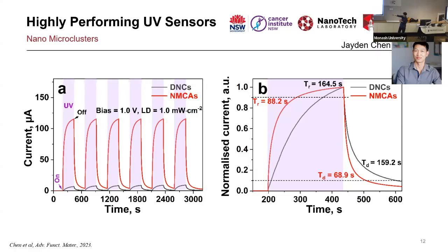And you can see the one in black is before we put the 5 microliter droplet, and the one in red is after we modify it. Both cases are exactly the same sensor and exactly the same material, because pure ethanol evaporates. So you end up with two zinc oxide films, before and after the process. And of course, it's a bit faster in terms of how it's responding, which we believe is because the electron can move much faster.